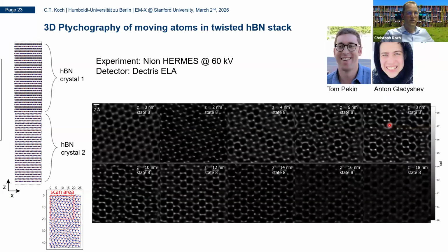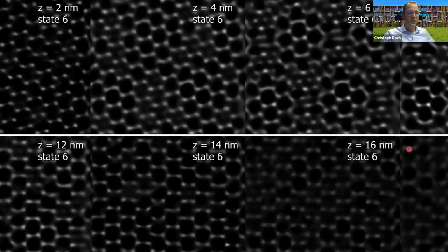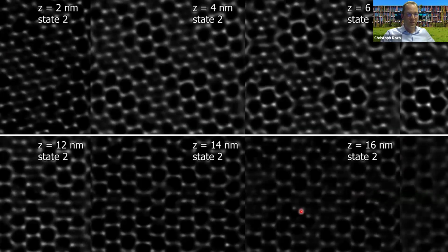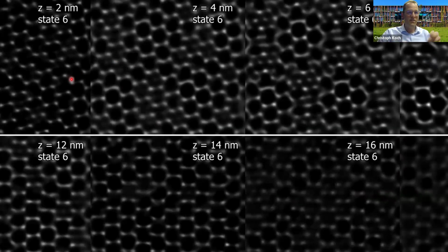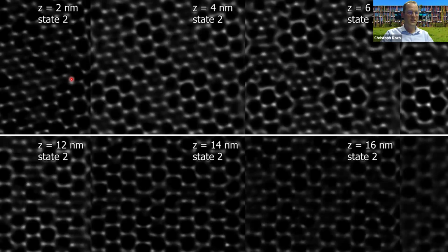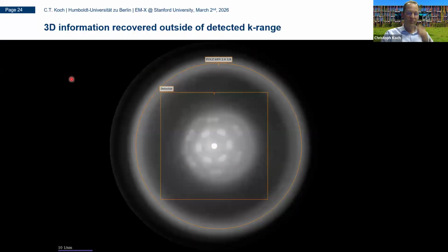But in addition to the 3-dimensional slices, so these are now the 10 slices that have been recovered. This is an older result. It's not the most recent one. So the Z resolution has actually become a bit better. But what I wanted to show you and what's most important to me here is in these slices, this is a top slice where you can see that the lattice is inclined a bit relative to the horizontal. And in the bottom slices, the lattice is actually aligned horizontally. But you can see that also the atoms are moving, right? You can now see really there is some displacement between the different objects that we've recovered. And these displacements are now being analyzed.